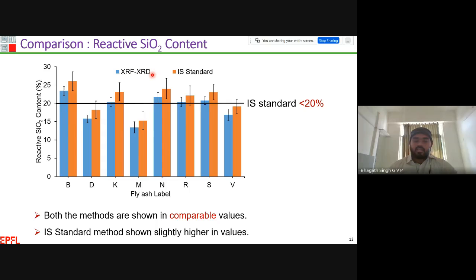The combined XRF XRD technique is a very straightforward methodology and does not require much time. In the case of the IS standard, we have to wait 24 to 48 hours to get the results for each individual fly ash sample. But the XRF XRD technique takes hardly 30 minutes to get the results for reactive silica. I am showing this particular plot because we can use either the XRF XRD technique or the IS standard methodology, and both show more or less similar results. But the IS standard method shows slightly higher values, so the reason may be that some of the particles are sensitive to the acid and may dissolve, and also we have to take proper precautions while doing the acid-based methodology.